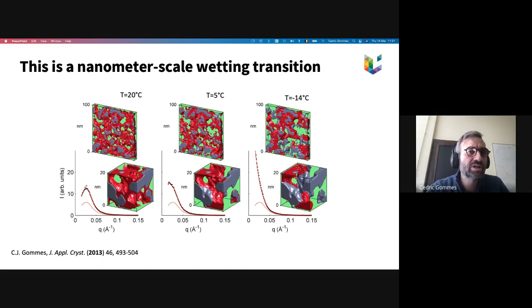And this is what is done here. So here you have the scattering intensity. The dots are the data, and then the red line is the scattering intensity of the reconstructed structures. Just for comparison, you see this dashed line here. This is what you expect in case the liquids would be completely mixed inside the pores. So there is a strong signal from this nanometer structure of the liquid. So gray is the solid, and then green is the hexane, and red is the nitrobenzene here.